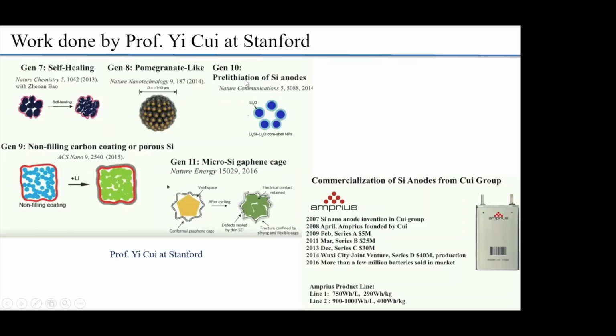Now, all of this effort, right? You can go into these papers and read more. All of this in an effort to understand and solve the problem of volume change, and then have a stable interface. Because if volume changes, the solid electrolyte breaks. If the solid electrolyte breaks, then it leads to more consumption of lithium and then degradation of the battery. And finally, they were able to come up with some commercial success.